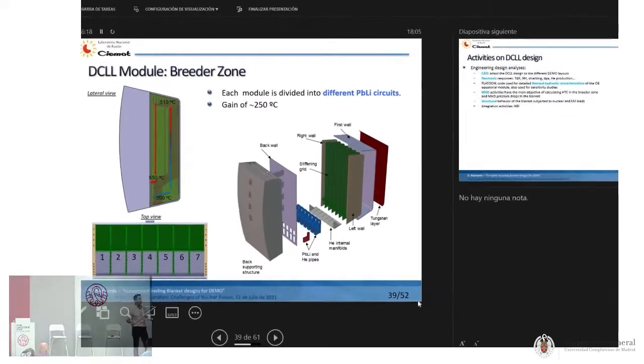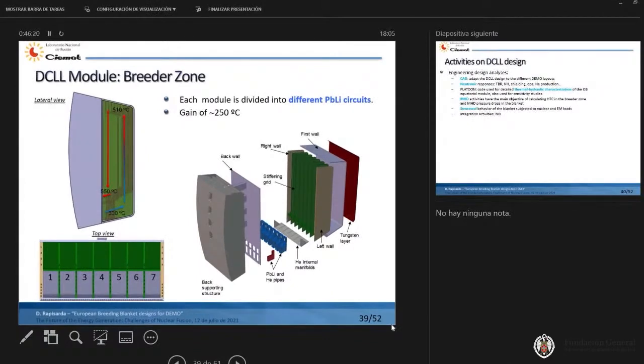Each of the modules is internally divided into different lead lithium circuits. Okay? The lead lithium enters through the lower part at 300 degrees Celsius. Here we have most of the gain due to the neutron interaction. We have nuclear heating here, okay? It makes this route and exits the module in this part at 550 degrees Celsius.